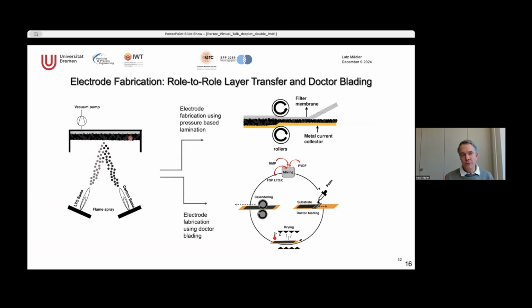And then we make one more step, which is also fascinating for me, and we call it lamination. So we take that filter here with the particle layer on top of it, and we can make that layer any size we want. And we put it on our metal current collector, and we laminate this particle film directly on the metal current collector. So there's no liquids involved. This is all dry. So out of the flame, everything is dry.